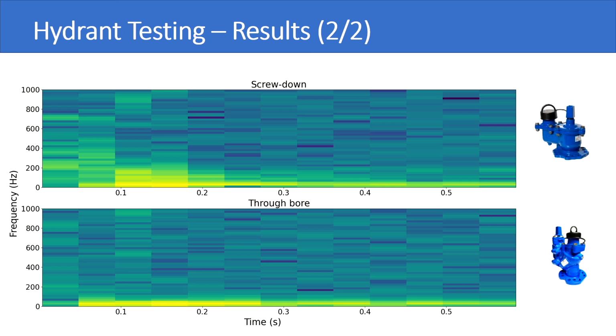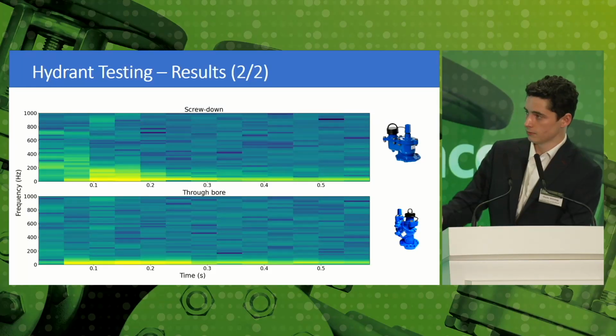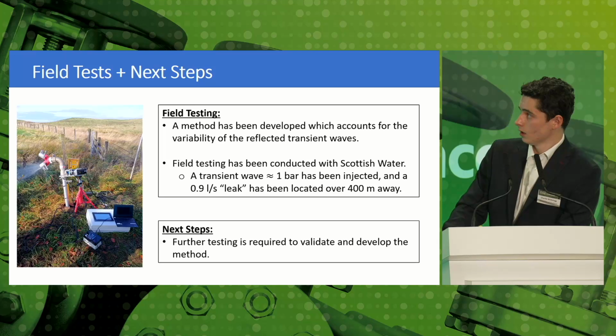Another way of looking at this is in the frequency domain. So this is a spectrogram looking at the frequency components of the signal across time, with the yellow areas indicating high energy points. So you can see with a screw-down hydrant, we've got some higher frequencies indicated by the yellow boxes present, especially early on in the signal. And that would somehow have to be accounted for if this was to be a viable method in the field, at least if we were going to model them.